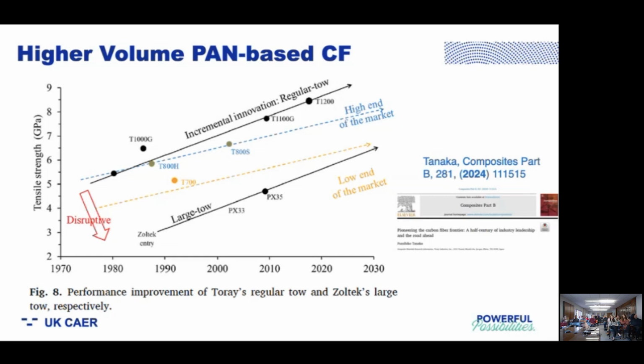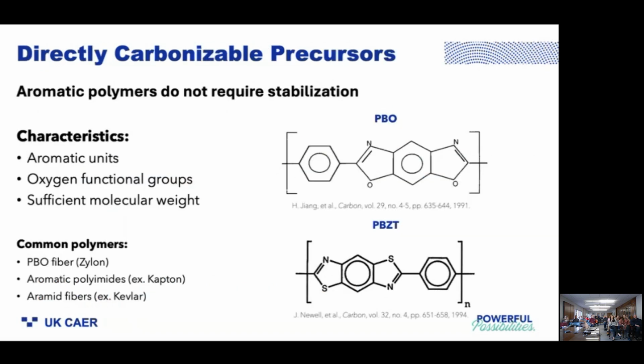If we increase to what's called a large tow, which might comprise maybe 50,000 or more filaments per tow, you can make more carbon fiber per unit time, which can drive its cost down. But you take a hit in tensile strength and you start processing more and more fibers at the same time, which limits some of its application. So that's what's going on currently in the industry.